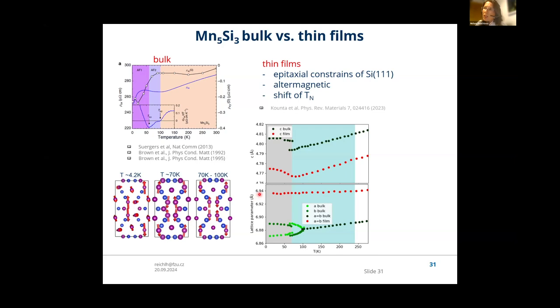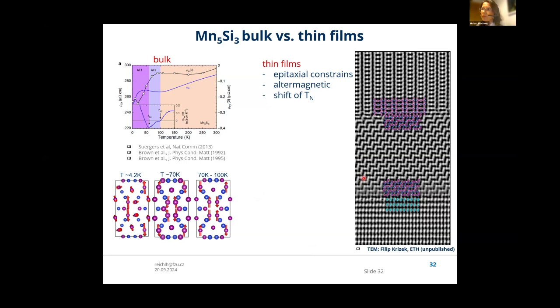unit cell. X-ray always measures the sample as a bulk, as a kind of average technique, so we also did transmission electron microscopy to look locally and to confirm that our hexagonal lattice is consistent with the localized picture, on a couple of spots, which we did by TEM. So we see that here the manganese silicide indeed forms this structure which we assumed by having the silicon 111.